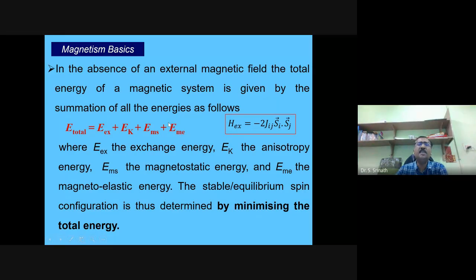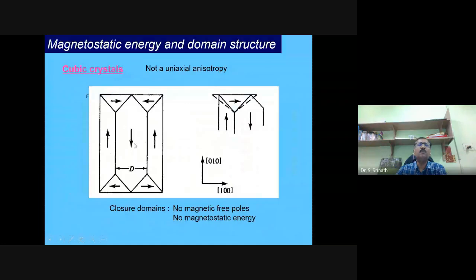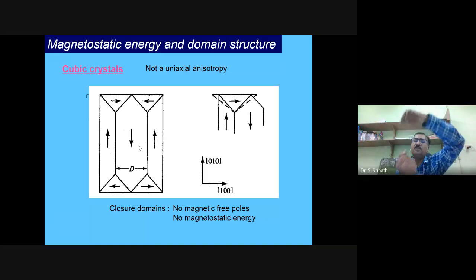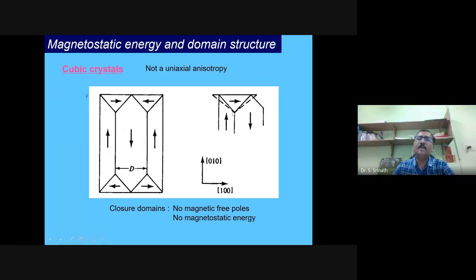So this energy also has to be minimized, which we never discussed so far. Now we are discussing. The role of this term is to make sure that the energy is minimum. I will not give too many details, but I'll give a physical argument here. When you apply the magnetic field, the specimen can try to elongate along this direction. At the same time, because of this orientation, the domains will also try to orient along that. So there will be a friction, basically a strain, which is developed at the domain boundary.